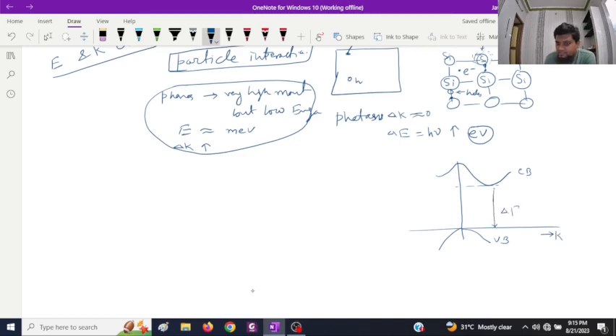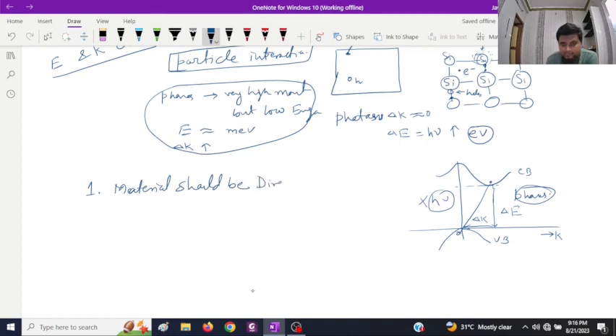And that is why it involves a finite momentum. So the probability that this electron will recombine with a hole with emission of h nu is very less probable. It is not that it is impossible, but very less probable. Then how does this energy go? This energy goes into lattice vibration, so in terms of phonons. So the first condition for light emission is that the material should be a direct band gap material, a direct band gap semiconductor. So this is one condition.